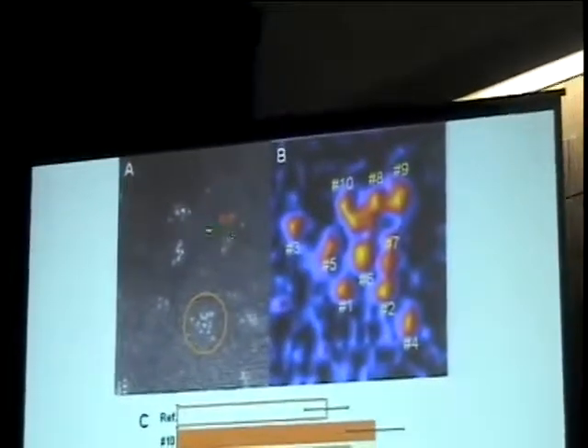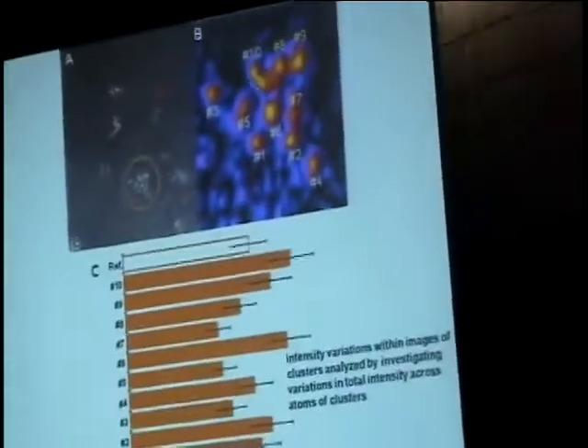And then she did statistics on all of this, and again, I won't go into the detail. She subtracts off the effect of the MgO support, which is variable from place to place, uses isolated osmiums, which remain in the gemisch after this synthesis, as a kind of standard, and then does the intensity analysis on the basis of that as a reference. And so consistently finding evidence of the number of atoms that I'm inserting in each of the clusters. In one of these you see a smear, and what that's telling you is that we're at the edge, because there's been substantial motion of one of those osmiums under the influence of the electron beam. So we're at the edge in terms of what we can resolve structurally with the microscopy.